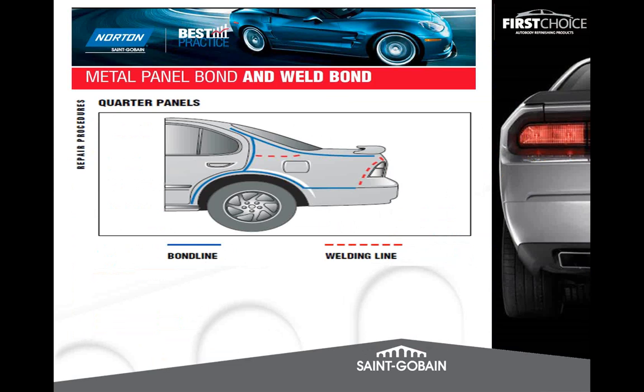Matter of fact, there's only one manufacturer that I'm aware of on the planet that will not let you use adhesives, and that's Toyota. They want everything welded. But all the other manufacturers will specify an approved glue, and it's typically an epoxy or an acrylic. So that blue line represents everywhere you can glue, and all of the OEMs recommend that you weld the taillight and where the old panel meets the new panel.